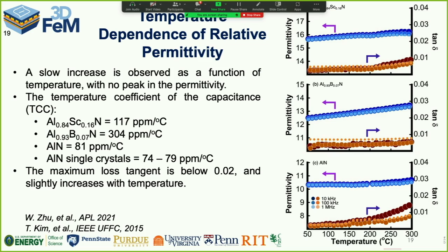But we can go through and do the baseline characterization. This shows the temperature dependence of the relative permittivity. These materials do not have phase transitions up to 300 degrees C. As far as we can tell, they do not have phase transitions below 1,000 degrees C. There are some first principles calculations that say maybe this material would become nonpolar above 3,000 degrees C. Well, that's cool. It's not a soft mode ferroelectric either. So totally new mechanism for making ferroelectrics. There is no nonpolar state at elevated temperatures.